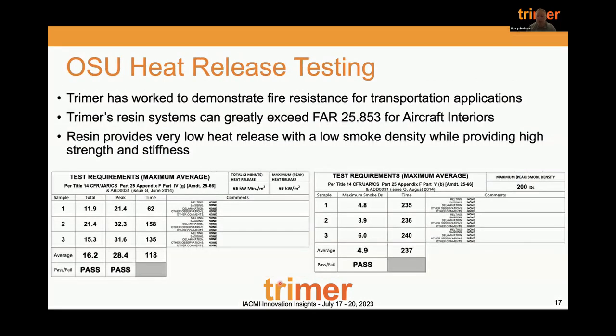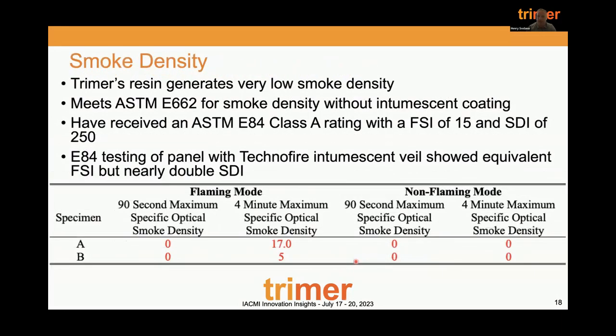If you look at OSU heat release testing, this is a test for aircraft interior, the mass transit. The requirement is 65 kilowatt per meter squared, and we're testing about 28. For the fire, the standard's about 200, or it is 200 in the corner there. And the average we're measuring is under 5. So extremely low smoke generation. And we can show that through ASTM testing as well. This is the E662. If you look down at this B, we're about 0 across the board, even in flaming mode. This easily exceeds the fire resistance for those standards.